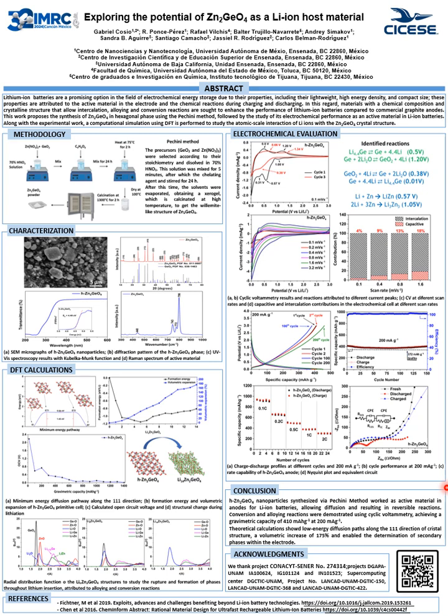A subtle increase of 30% in charge transfer resistance was noted between the fresh electrode, prior to ion insertion, and the charged electrode with ions inserted, attributed to an increase in electrode volume caused by ion insertion. In addition to the experimental work, a computational simulation study was conducted using density functional theory (DFT) calculations.